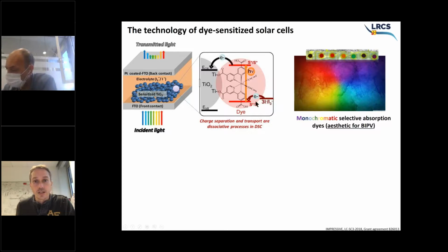And then, if I take the example of the ruthenium complexes, this ruthenium complex will be oxidized, from ruthenium 2+ to ruthenium 3+, and then it will be regenerated by hole donation to the redox mediator. So typically the redox mediators are based on iodine/iodide, or often now on cobalt polypyridyl complexes.